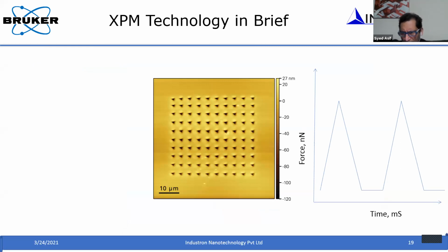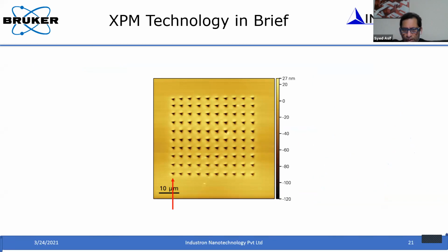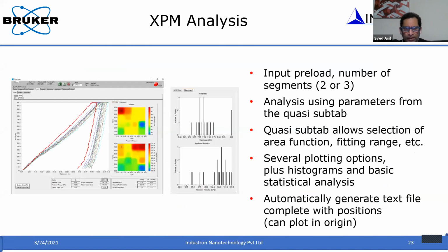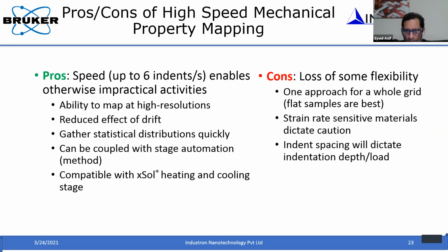For example, in a typical load profile, because we wanted to reduce the amount of time spent on each indentation, we use a simple load profile, loading and unloading very fast. Then you pause for some time at very small load or at zero load. During that pause time, you move the tip from one position to the next, and you do that continuously, for example, 6 indents per second. Then you get this load displacement response. You take this load displacement curve and use the same Oliver and Pharr method of analyzing the unloading curve, and then you can plot hardness and modulus in a map form.